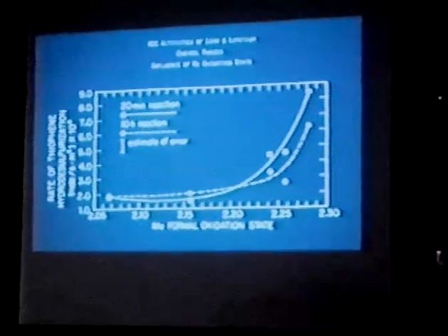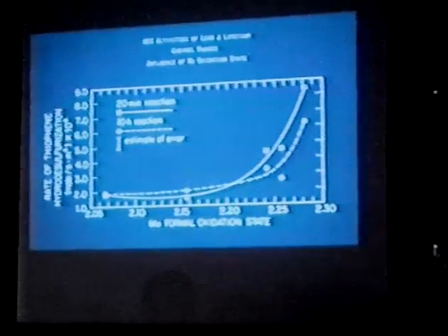There's only one slide I think that I will talk about before going to the conclusion here. The other thing that I'd like to point out for the Chevrel phase compounds is that they're rather selective catalysts, and if you look at the ratio of HDS to hydrogenation, just using 1-butene as a very simple molecule to look at hydrogenation, these catalysts preferentially do a lot of hydrodesulfurization compared to hydrogenation.